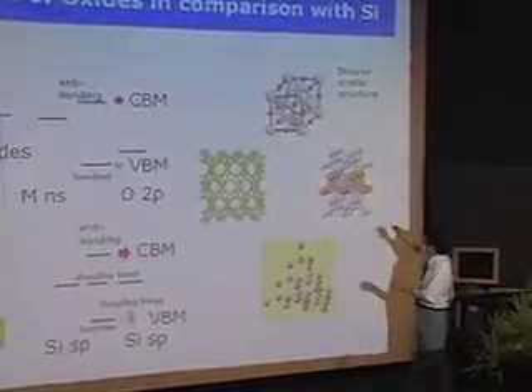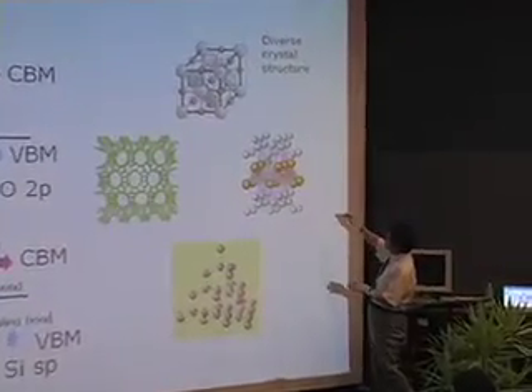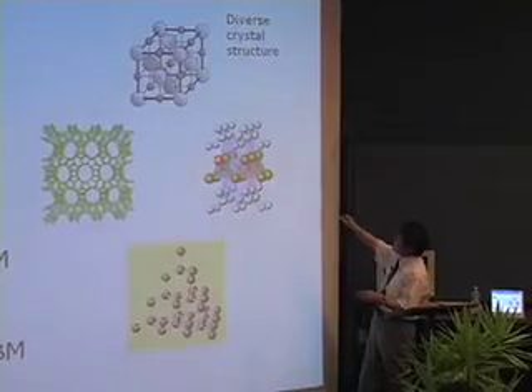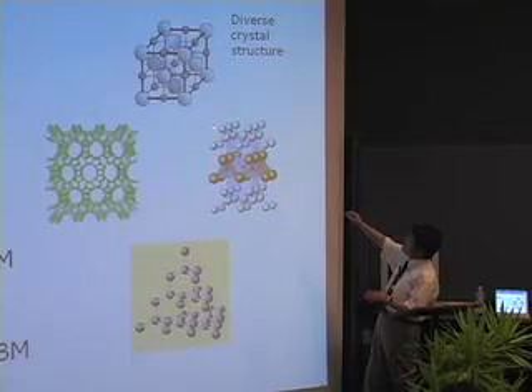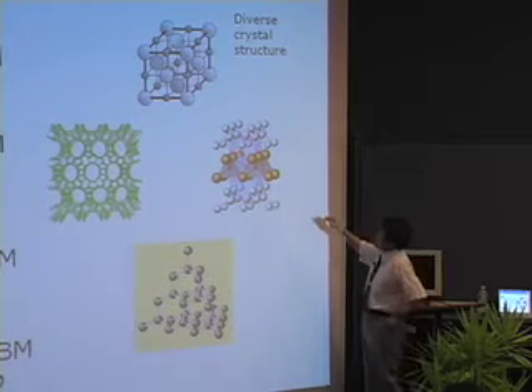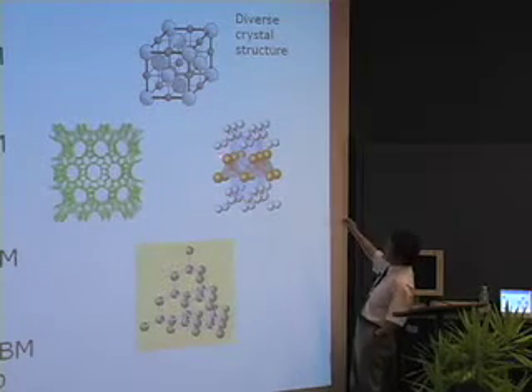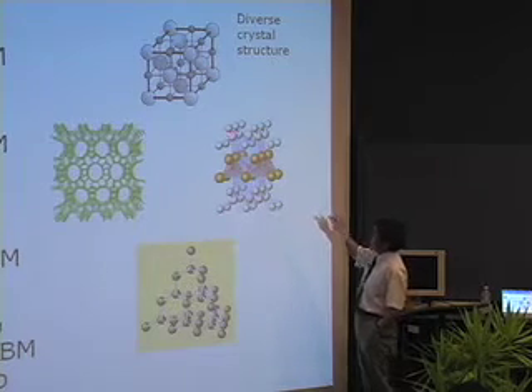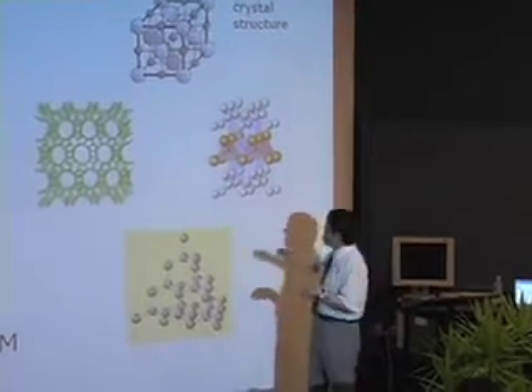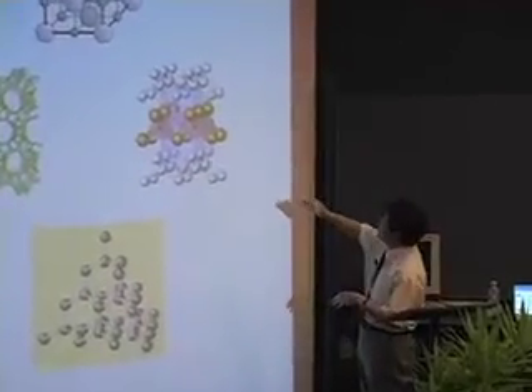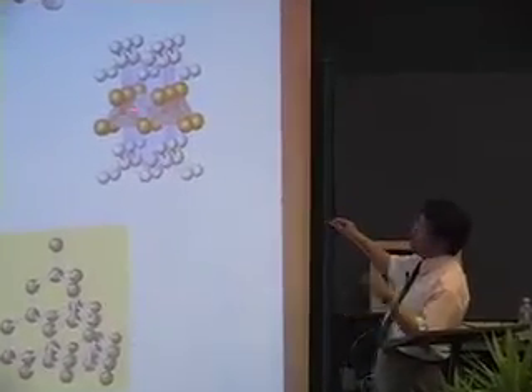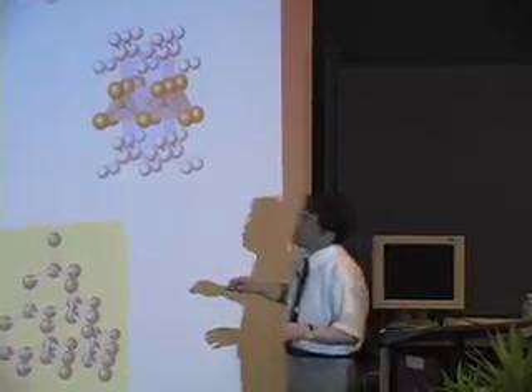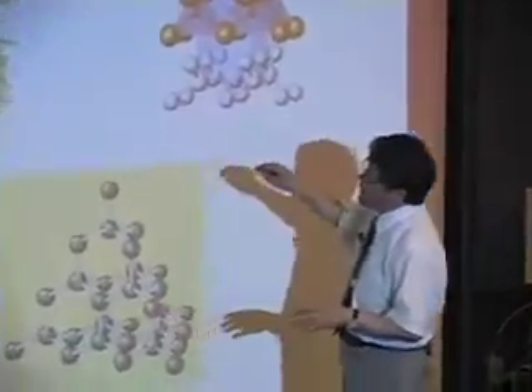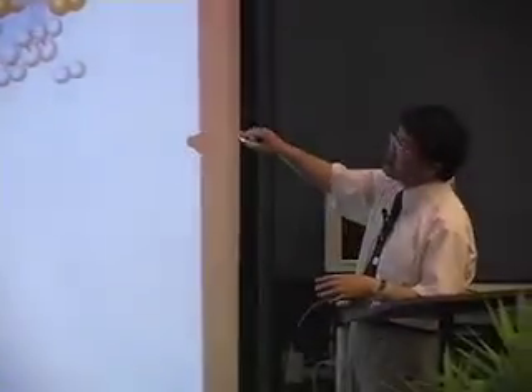In layered structures, if these layers are semiconductors with a narrow gap and these are insulators with a large band gap, the electrons are confined in this layer. So this kind of material may be regarded as realizing a two-dimensional electronic structure. Our strategy is to extract intrinsic properties by utilizing such nanostructures embedded in the intrinsic crystal structure of oxides.